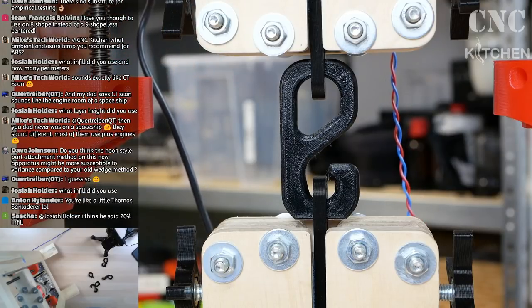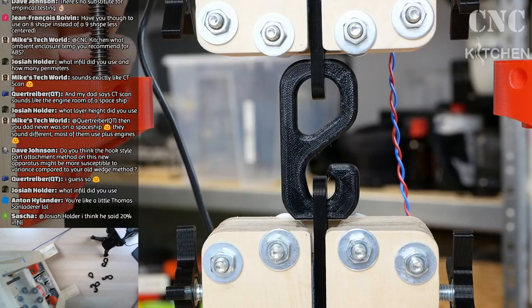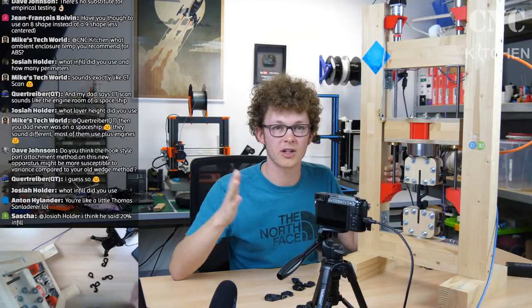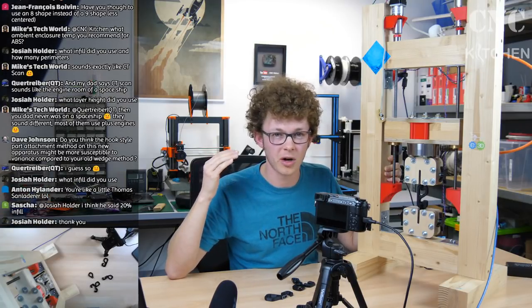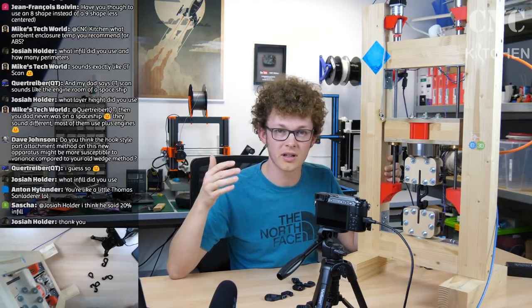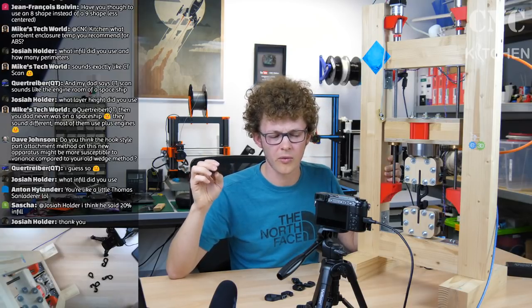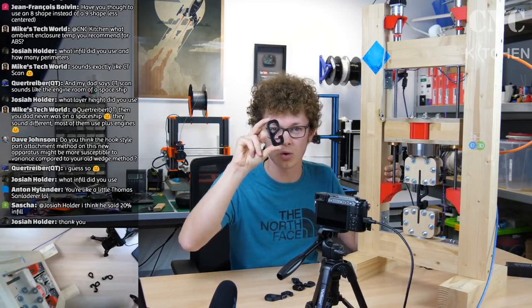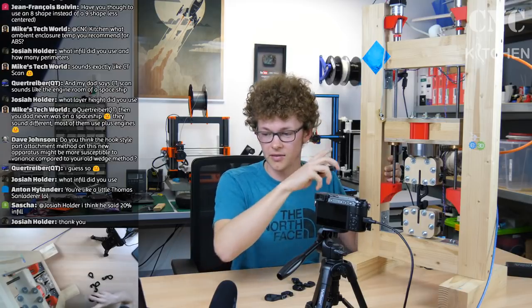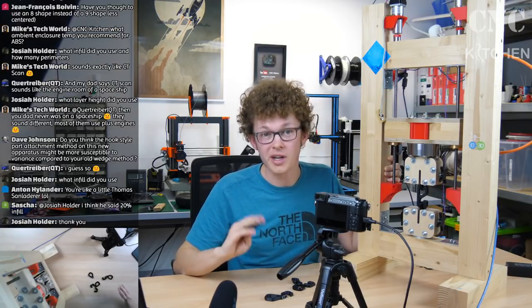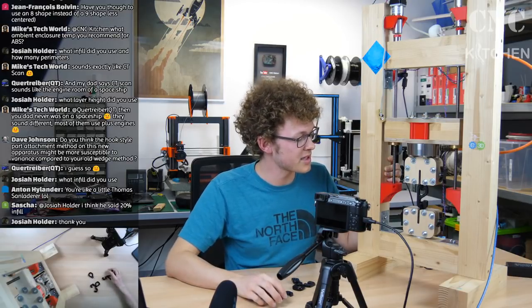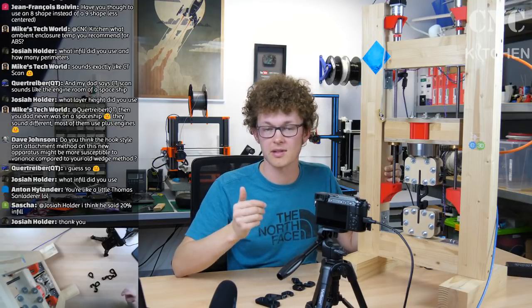Yeah, the infill was just 20%. So the 20% infill should not really add that much to the strength of the part. I did not want to print them with 100% infill. I do this with my standard tensile test specimens, but the values you get from there are really hard to apply. I wanted to find a way how I can really compare two different materials and how the amount of flex, the amount of yielding a material can do affects the real strength of the part. So as I said in the beginning, Wolf 3D were testing material strength with hooks which looked kind of similar. They did not do it as scientifically as with a tensile testing machine. So I more or less adapted this method and do these tests on my tensile testing machine. So we should get much more comparable values in the end.